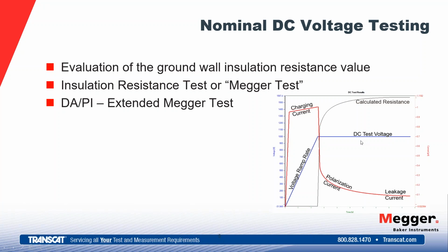And again, this voltage that we're holding at will be determined by the nameplate voltage of the motor, either at or below that. IEEE 43 speaks to recommended test voltages there, and they'll be at or below the nameplate of the motor. So as we ramp up to that voltage, basically charging current is what we're going to see as mostly dominating the current that we're measuring. So we're going to allow time to pass, and as time passes, we don't change voltage. Our current at that point, what we predominantly measure is going to be absorption current or polarization current. And we're going to let a little more time pass till we get to the end of our 1 minute.